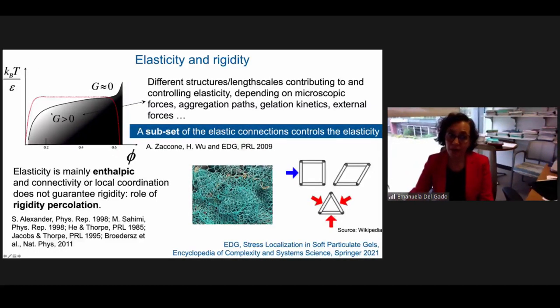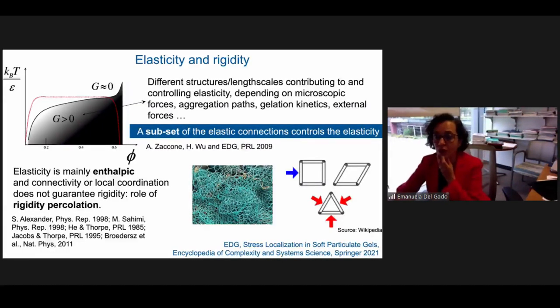And then somewhere under this region, because you need the aggregation processes to be strong enough to basically initiate the gel formation, I'm going to see some transition from a liquid-like to a solid-like behavior. But which type of local structures, in which way they will assemble on larger scale and then determine this frustration, how does this happen will depend not only on the volume fraction of the solution, so the amount of solid material that I put in, and on the strength of the interaction, but also on the kinetics, on how I go through this line, or I cross this region,